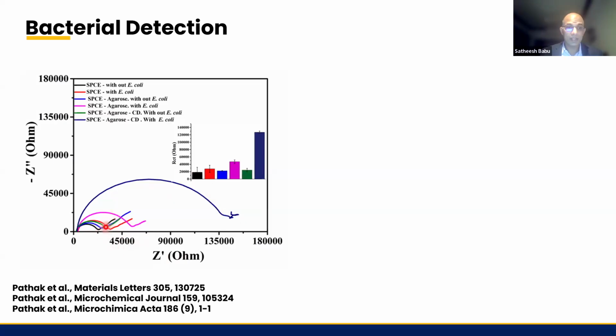So we find that these were the bare electrode with the E. coli sample, and the agarose modified electrode and the corresponding electrode which is dipped, and then we measured the impedance here. Then we have the electrode with carbon dot, and that is actually studied for the bacterial sample, where we could find a huge increase in the impedance.